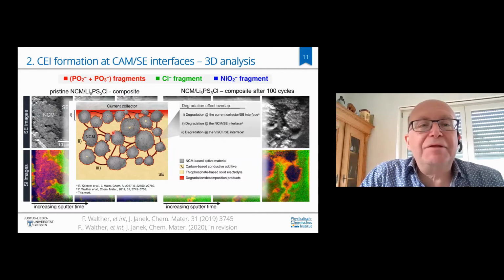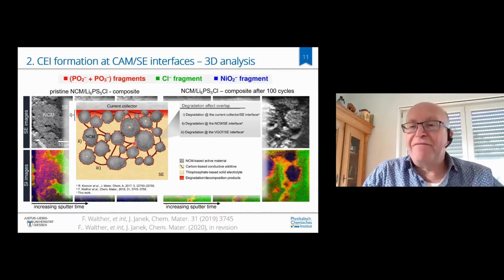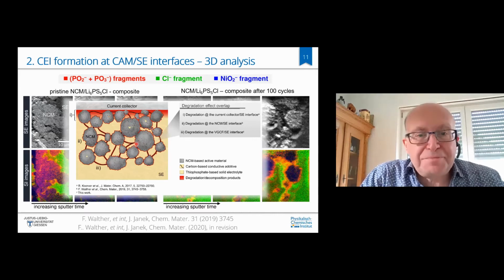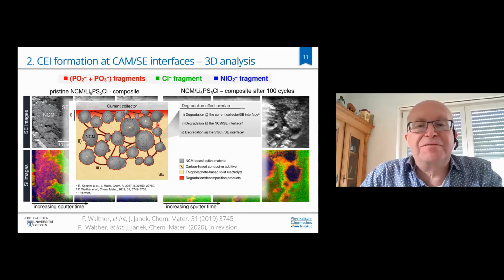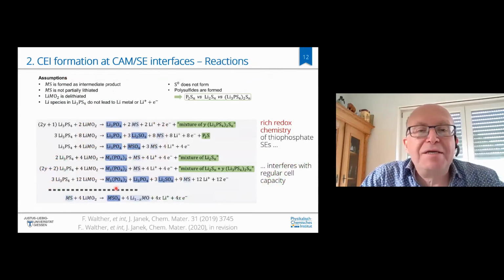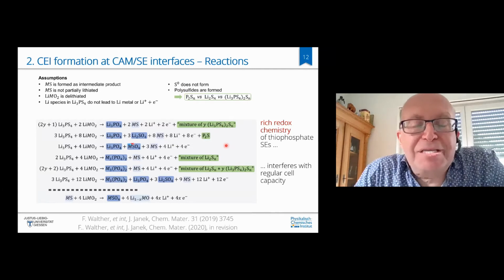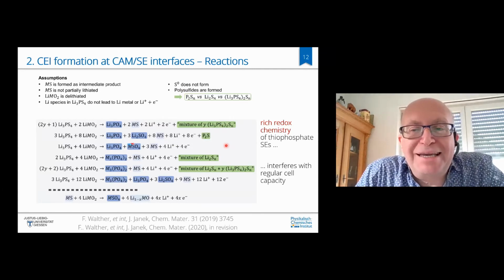Now, if you have a cathode including a carbon additive, you may protect your cathode particles, but if you use carbon fibers or whatever carbon conductive additives, they also have the potential of the cathode. And we were able to show by XPS that the electrolyte around the carbon additives is also being oxidized, and also at the current collector. So there's lots of degradation going on. This can be clarified and analyzed in detail. So we were able to show that, of course, during oxidation, phosphates and sulfates form out of the sulfide electrolytes, and polysulfides that may even in the extreme go to sulfur. And this is interesting. That means that the electrolyte is not only degrading, it adds to the capacity. And I know that some Chinese groups try to use that by using the electrolyte itself as an active material.